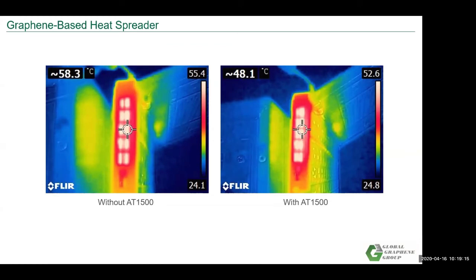And this is an actual example where we put our AT1500 into laptops. Without AT1500, you can see that the temperature can go as high as 58.3 degrees Celsius. With our AT1500 heat spreader, it dropped about 10 degrees Celsius, which is very effective for heat dissipation. Definitely keeps the laptop cooler.